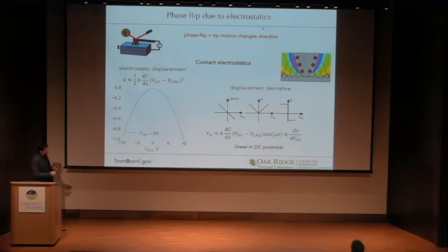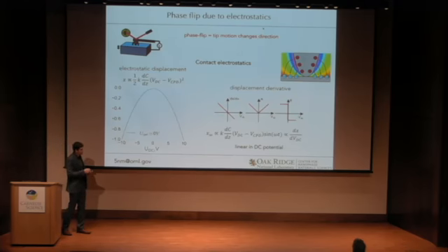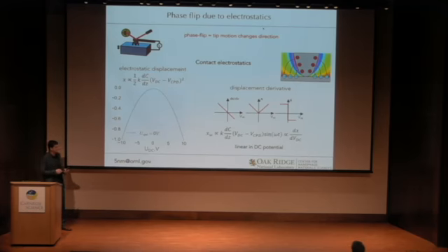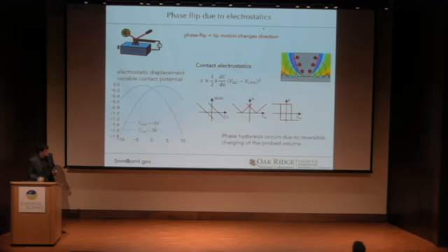And of course, the derivative of this is a straight line with a negative slope, and the amplitude signal will look like a V sign. But unlike the piezoelectric signal, the definitive feature of electrostatics is that it scales linearly with applied DC potential. That's why we put emphasis on in-field observables. Moreover, electrostatics will become hysteretic in phase if this null potential starts to change during the experiment.